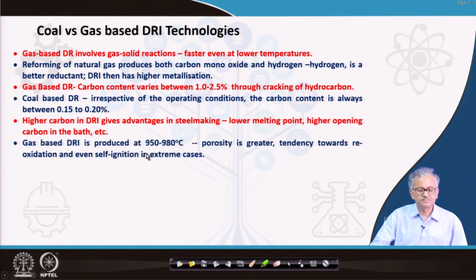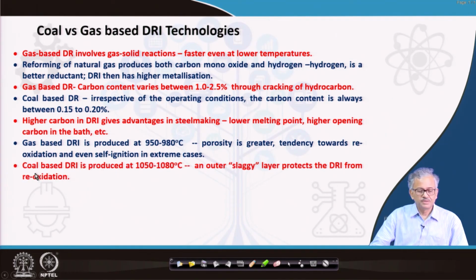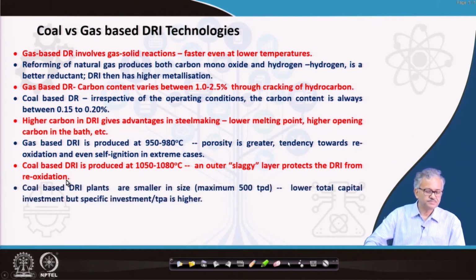Obviously, high carbon DRI gives an advantage in steelmaking: lower melting point, higher opening carbon in the bath. And as I said, the gas based DRI is very prone to self ignition and reoxidation. And the coal based DRI is protected by a slaggy layer outside, as I said.